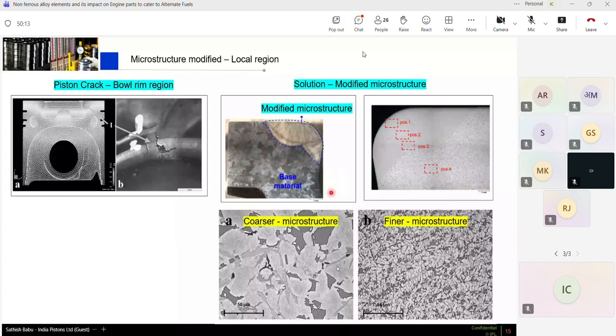You can see on the right-hand side of the photo the difference between the coarser and finer structure. This kind of finer structure will be very helpful and it will make the silicon particles very much reduced, and it reduces the intermetallic phase gaps, and it improves the finer grain sizes, and is very helpful in reducing this kind of cracks. Some analysis says that there's a difference of grain structure between this modified microstructure and a normal casting microstructure. So this kind of technology, with a modification in the casting structure, is nowadays used by all the customers